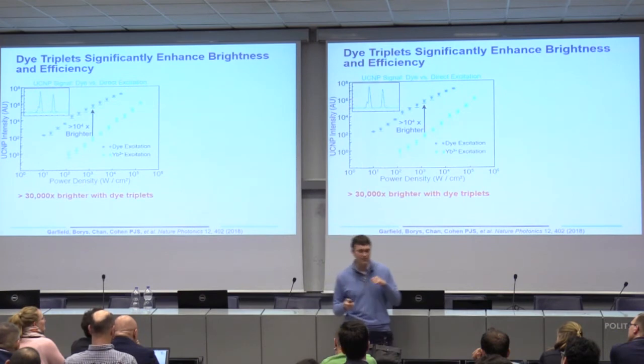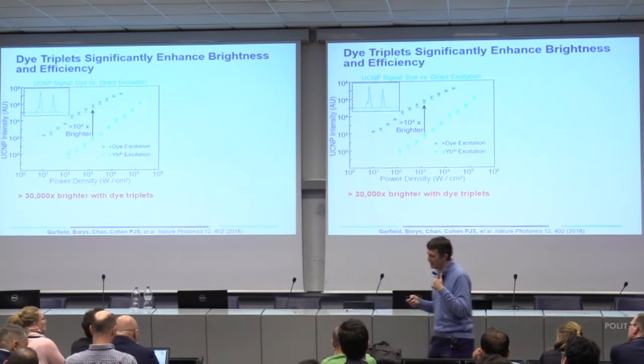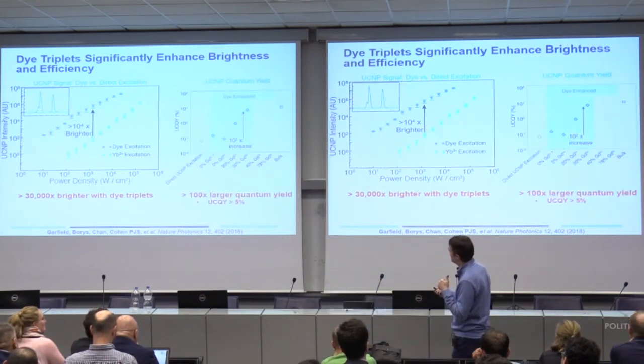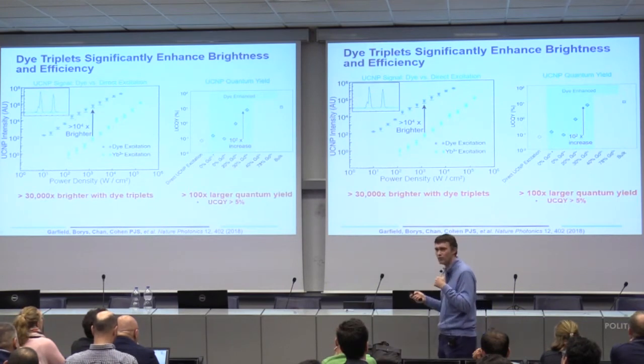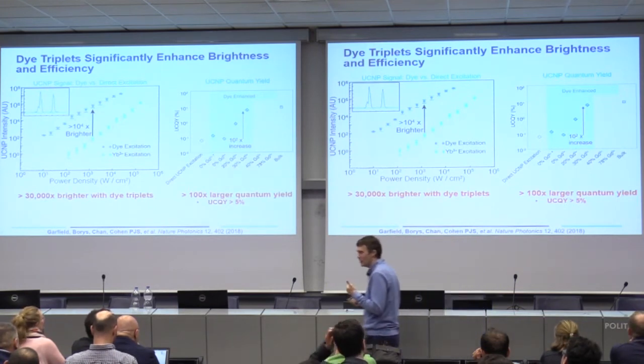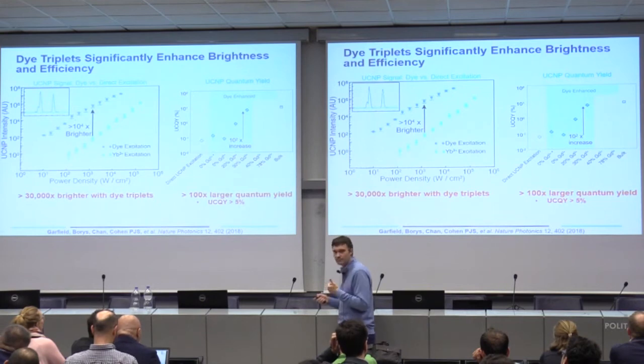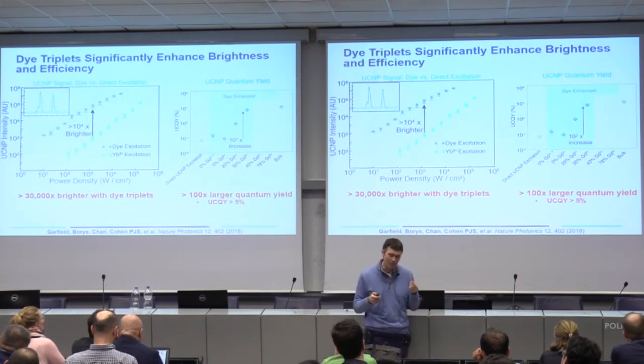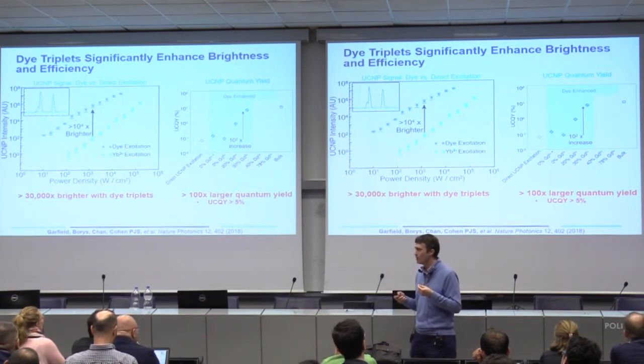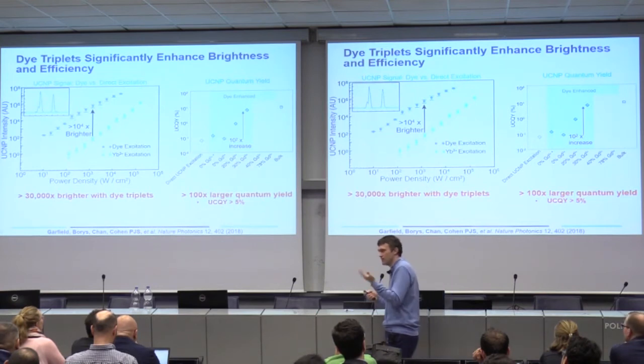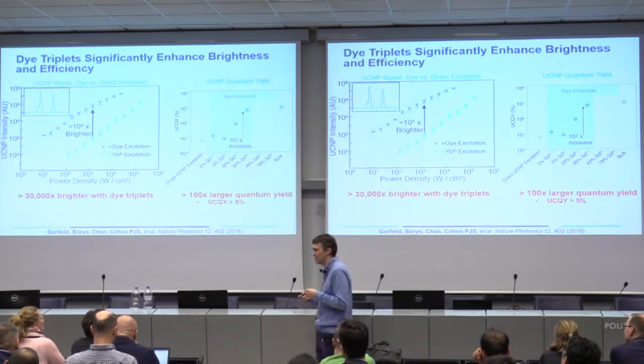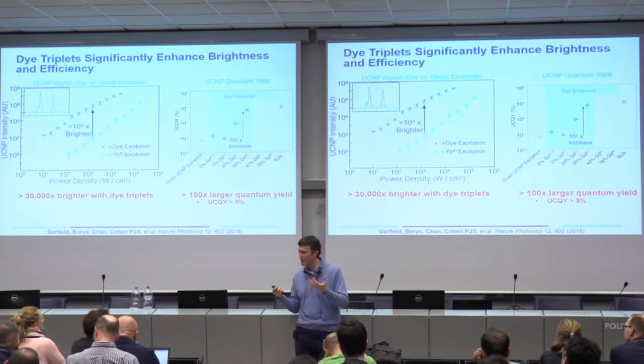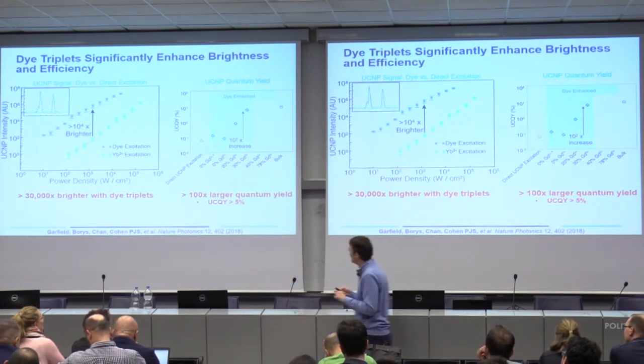What actually is more impressive to me than the 30,000 times brighter is the fact that what happened was the upconverting quantum yield improved by 2 orders of magnitude. So up to almost 10%. So they went from 0.1% to 10% upconverting quantum yield. So this is a nonlinear process with this sort of 10% quantum yield. So now you're starting to approach behavior of like a regular dye molecule, except it's a nonlinear particle, right?